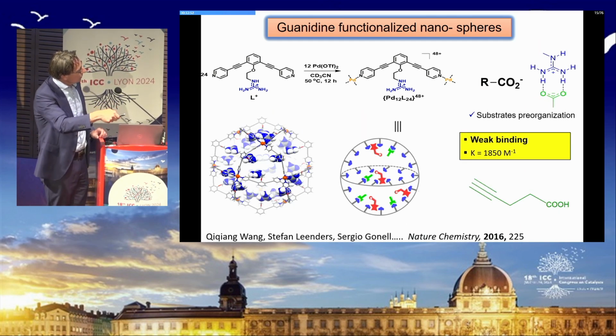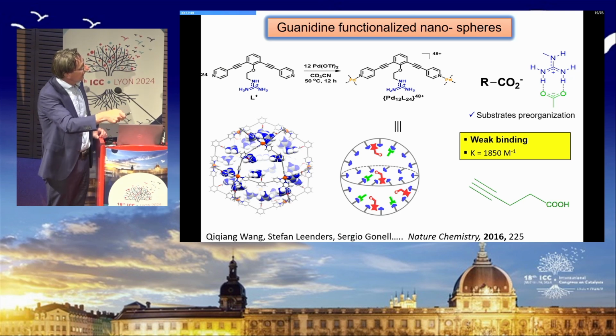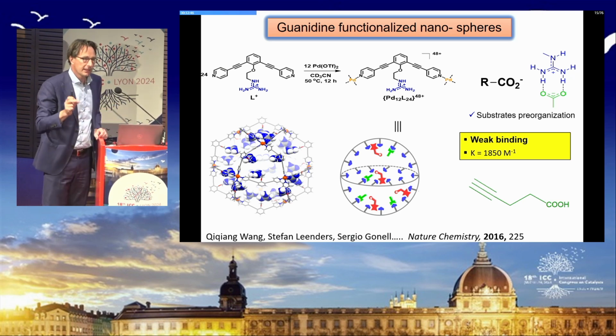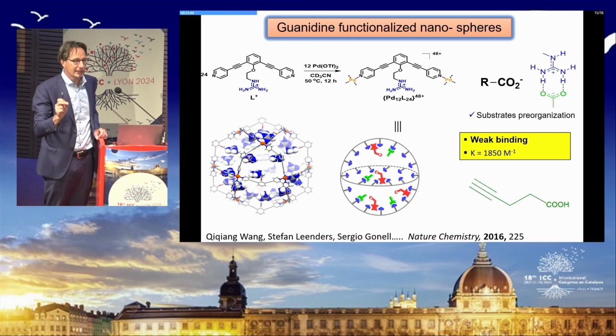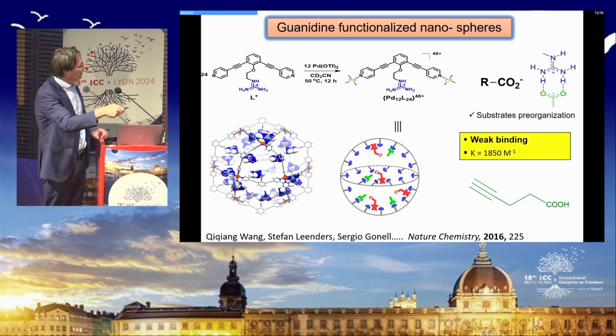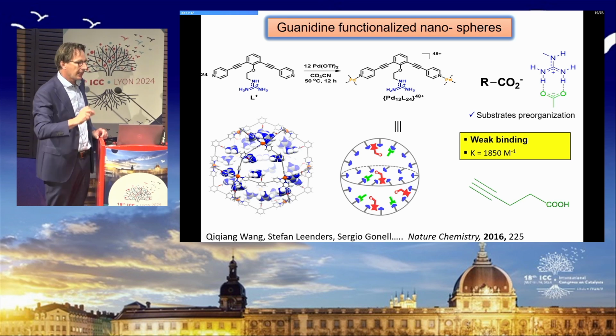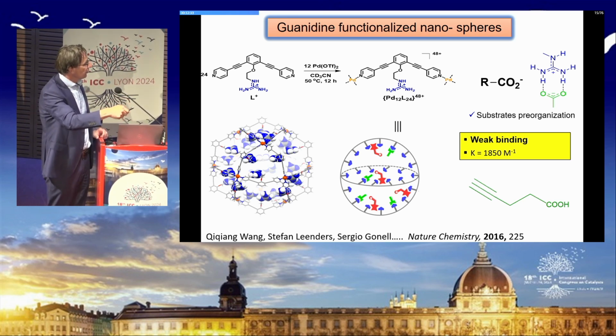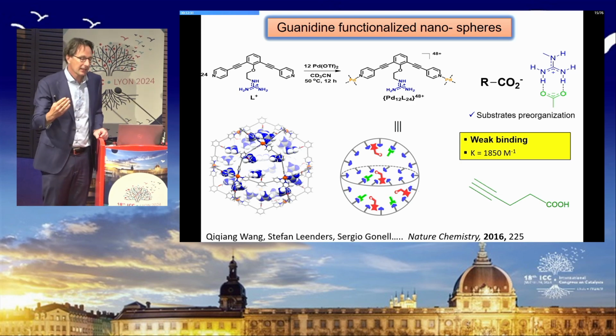Interestingly, you can also use substrates that have a binding motif, and this binding motif is a carboxylate, and carboxylates bind as well, but they bind monotopically, so they bind more weakly. So we have a situation where we can bind strongly a catalyst by supramolecular interactions, and we can pre-organize our substrate to the remaining binding sites without kicking out by competition our catalyst.